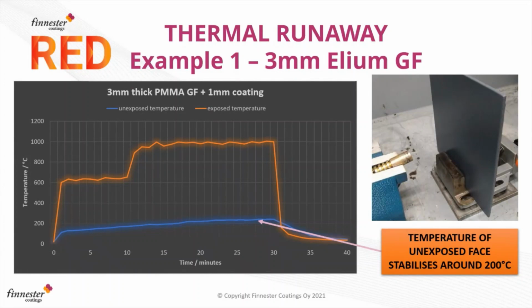In terms of the thermal runaway testing we've done, following a very similar method to the one that Ari introduced earlier, we've been running our Bunsen flame, measuring temperatures on the outside of a plate and the inside of a plate. Of course, we're now talking 3 millimeters instead of 15 or 20 millimeter thick materials. Again, one of our favorites, the Elium material from Arkema, the polymethyl methacrylate glass fiber material. Very interesting results here, where we've got outside temperatures of 1000 centigrade for 20 minutes, and we're just over 200 centigrade on the unexposed surface.